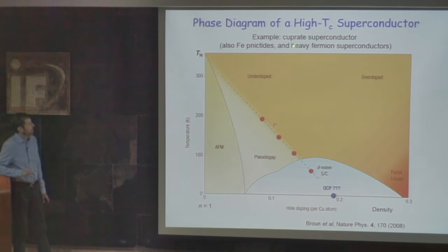This is a phase diagram of a generic high Tc material. This happens to be a cuprate superconductor. There's temperature on this axis and hole doping on this axis. So for us, hole doping means that we're removing particles from the system so that there are more holes in the lattice, more vacancies in the lattice. Now, at an undoped lattice, where we have exactly one particle per site, this phase diagram of cuprate superconductivity says there's this region of antiferromagnetism, which also turns out to be a Mott insulator that I'll discuss in a moment.